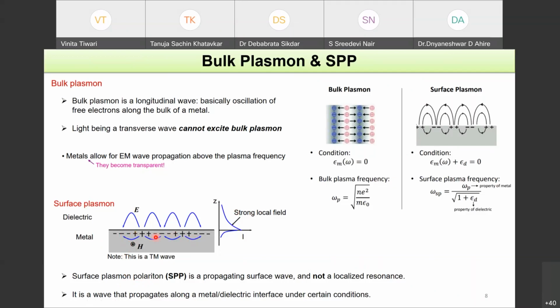And where does it exist? It exists along the metal dielectric interface. And does it happen in every condition? The answer is no. You have to satisfy certain conditions and then you can get this surface plasmon frequency. As you can see, the resonance frequency omega sp depends on omega p over square root of 1 plus epsilon d. Here epsilon d, the choice of the dielectric, plays a role in deciding the surface plasmon frequency. And what is omega p? That is the property of the metal, which we cannot change, right?